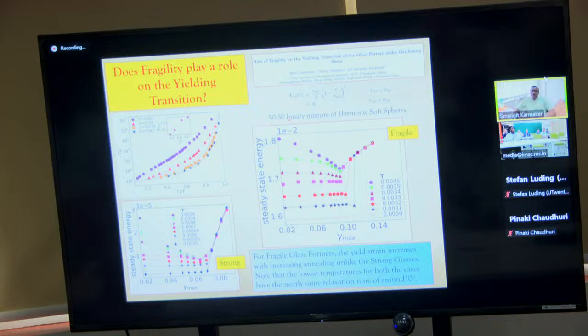So this is a 50-50 binary mixture of harmonic spheres. At a density of, let's say, 0.681, you get a state which is more strong-like. And this state you can take and cool to get a zero temperature glass and look at its dynamical properties. But if you take a density of 0.943, which is these black stars, then you get a very fragile liquid, and you can quench this liquid to get a glass generated from these fragile liquids. So we repeated this same oscillatory shear on these samples, and for the strong case, what we found is that the phase diagram or the annealing property changes significantly. One interesting point is that if you start from poorly annealed, then your annealing goes on and on and on. At some point it stops, and beyond this oscillatory amplitude you start to yield, and there is no longer any annealing.